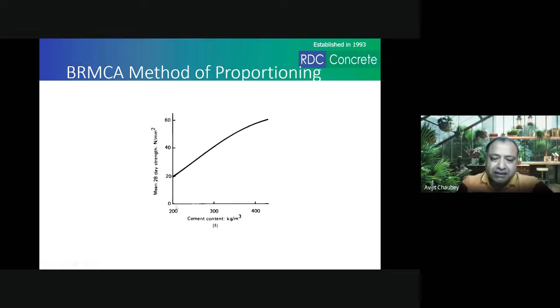You see, this is how you do the BRMCA method, the family of mixes method. You do trials with different cement contents, with the same water content. So you get different strengths, and you plot a graph. If you want a strength of 25 MPa, just draw a line from 25 to this graph, and then draw a line down. You will come to know that for getting 25 MPa strength, I require a cement content of somewhere around 220 kg. This is how the BRMCA method works. This is the most accurate method.